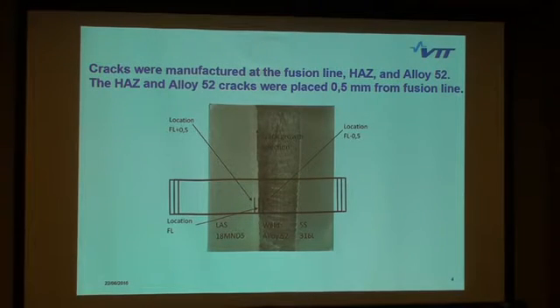This is an important concept, where the cracks were manufactured, because when I start to talk about the results, you need to remember these pictures, otherwise you will be kind of lost. The cracks were manufactured at the fusion line, in the heat affected zone, and in the alloy 52 weld metal. The weld metal crack and the heat affected zone crack were manufactured 0.5 millimeters from the fusion line. But this is an issue that I will later explain more accurately.